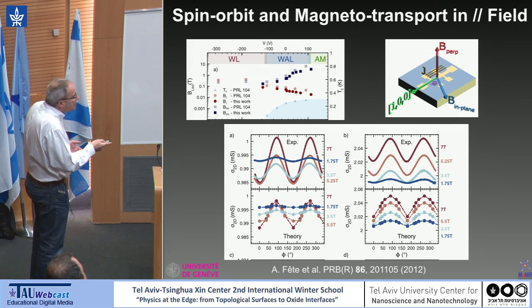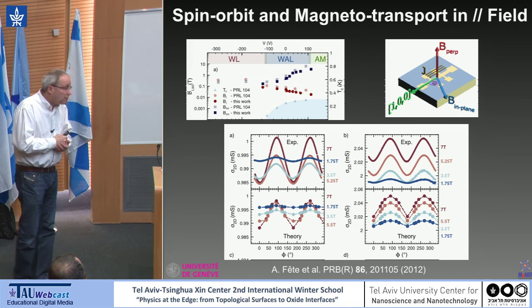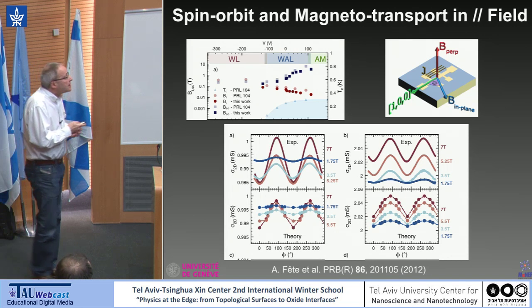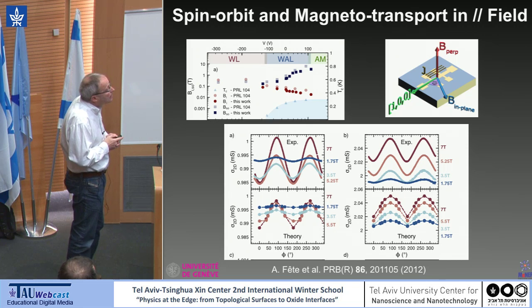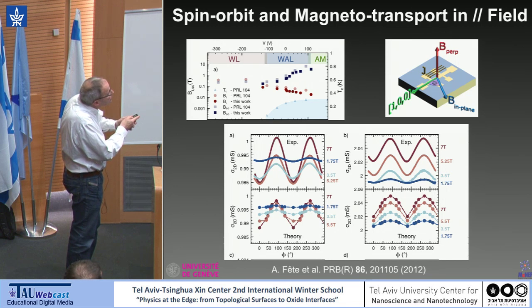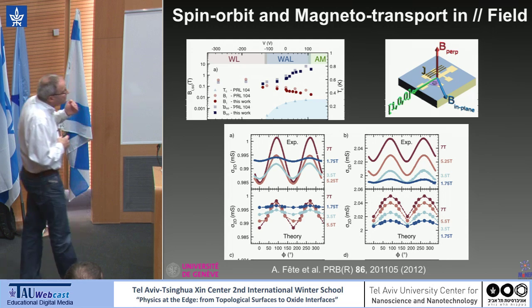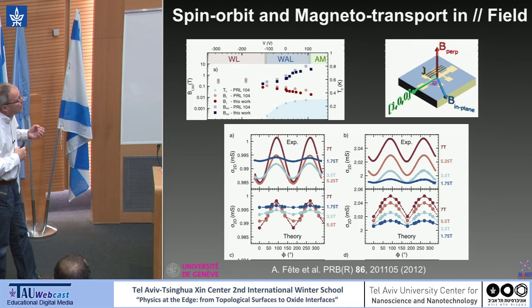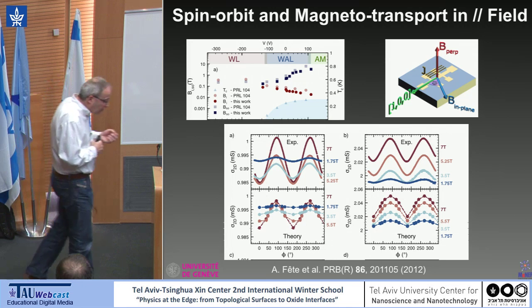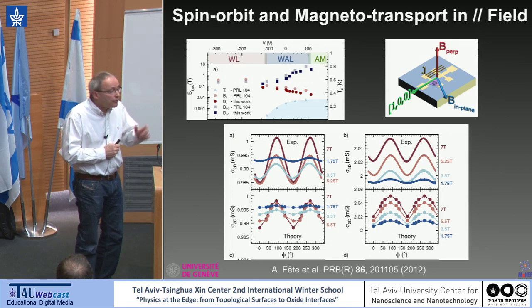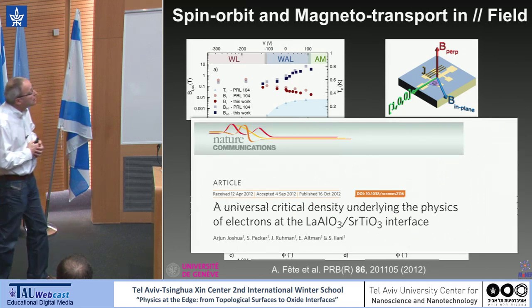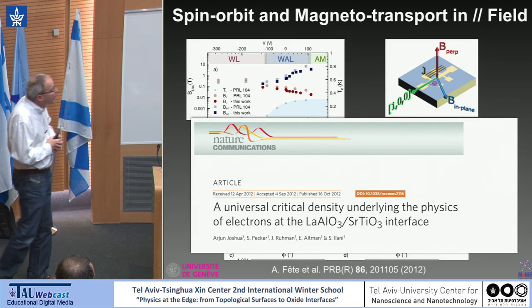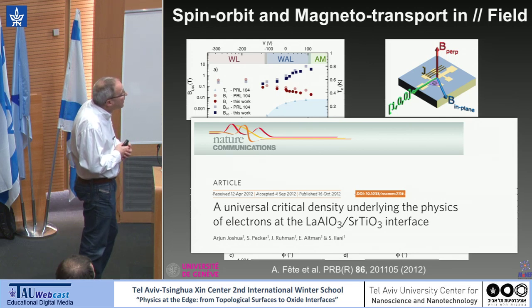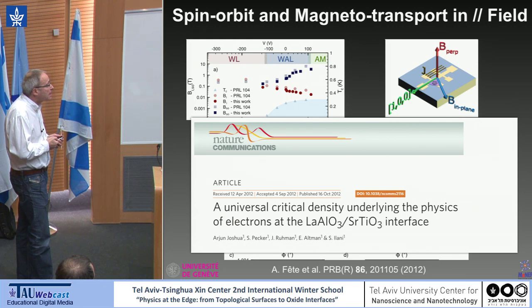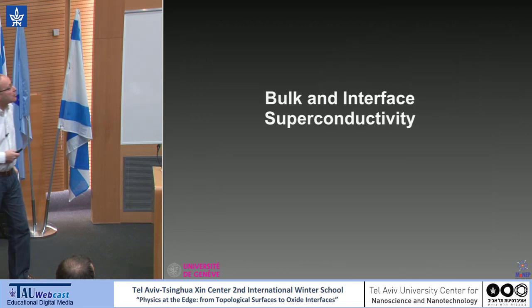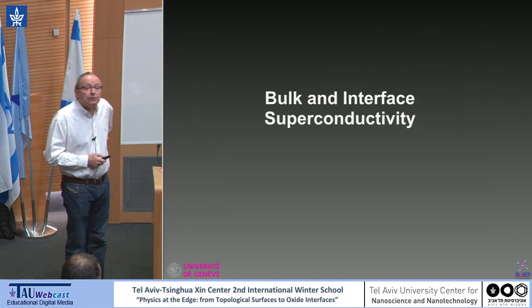For instance, in this paper, we looked at oscillation of the magnetoconductance in plane, and these oscillations we believe are linked to XZ YZ bands, and they die when you leave the superconducting doping regime. And also, the measurements show that the different bands have different mobilities. Let me also mention here the work of Shahal Ilani at the Weizmann Institute, who has been working a lot on this. All this will be important now for the discussion of bulk and interface superconductivity.